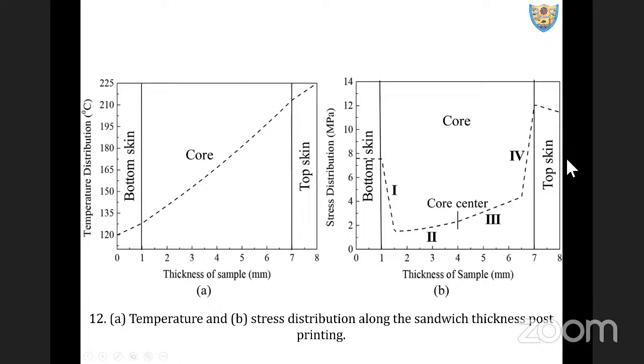Whatever printing parameters we mentioned as suitable, the same printing parameters and same boundary conditions in the form of temperature we applied, and simulated a finite element model. This is what we get as the temperature distribution, and this is what we get as the stress distribution. Experimentally, getting the stress distribution in the sample is difficult, and that's why we chose this finite element simulation route, wherein you can see at the skin and the core, there is a drastic change in the stress.